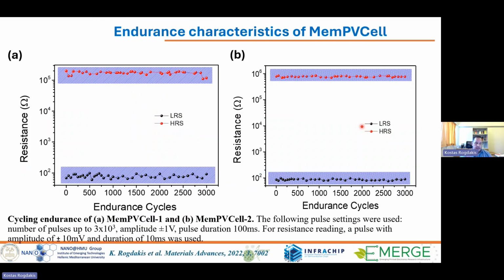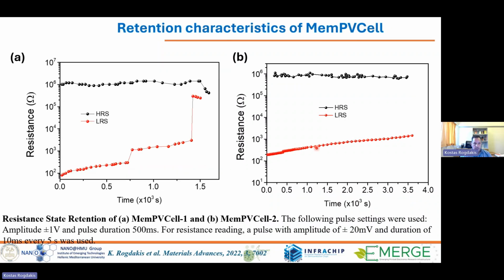And we demonstrated typical protocols for memristors. It's the endurance characteristics of the device. What we call here endurance is we send electrical pulses and switch the device from a high resistance to low resistance, high, low, many times. And this is indicated by the cycling number. So we repeated this cycling from high to low 3,000 times with no degradation evident in our measurements.